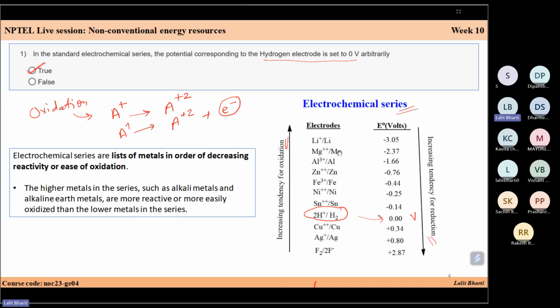So that is why you cannot take lithium in normal air, because if you take a foil of lithium in normal air, it will directly interact with the air and the moisture, and it will give you an explosive reaction. So that is why lithium and sodium, these kinds of metals, are kept in a glove box where the environment is either inert or filled with a particular gas. So they will not interact, and the H2O levels are minimized to a very, very low number, let's say less than 0.5 ppm. ppm is parts per million.